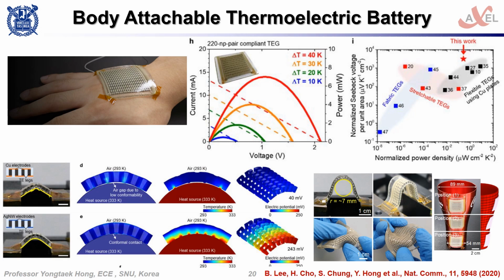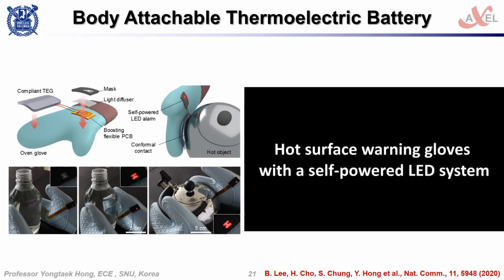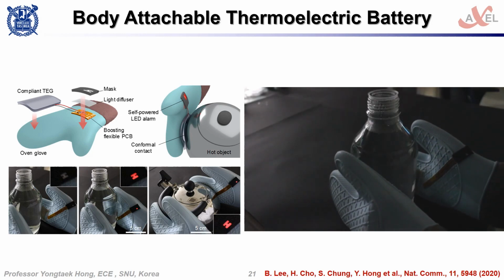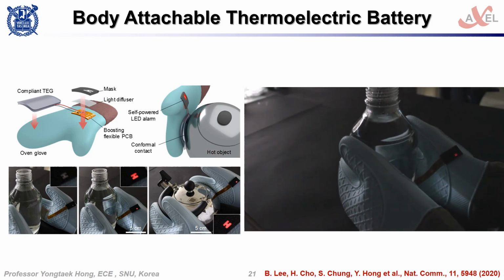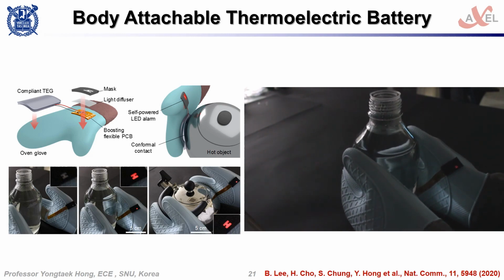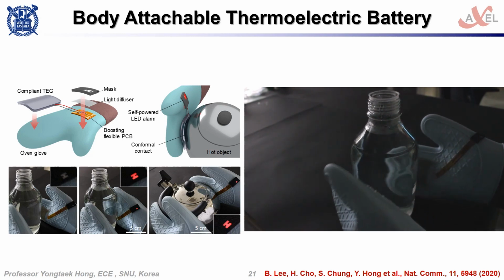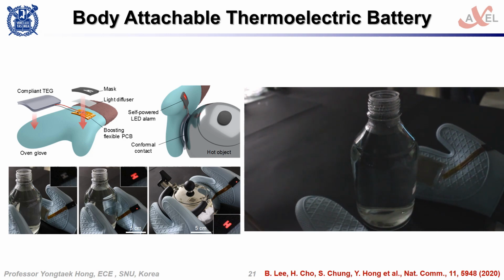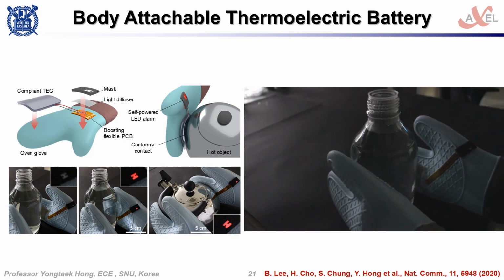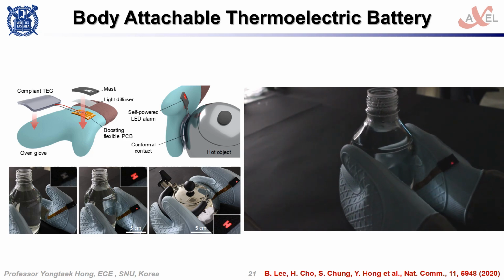The 220 NP pair showed much better performances than previously reported flexible and stretchable thermoelectric generators in terms of both Seebeck voltage and power density. High conformability guarantees perfect contact on any complex curved surfaces. We successfully demonstrated the hot surface warning gloves, which show a hot signal when touched on hot surfaces of a kettle or a bottle containing hot water.